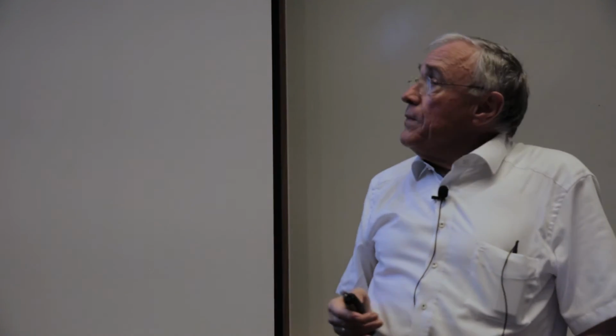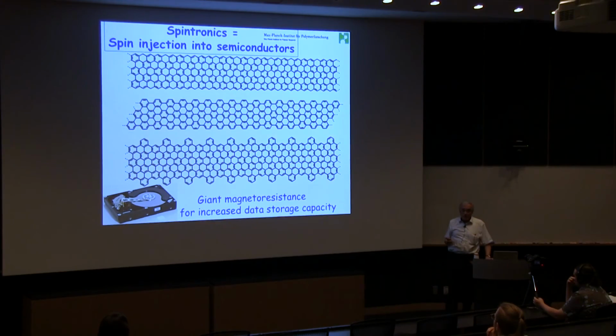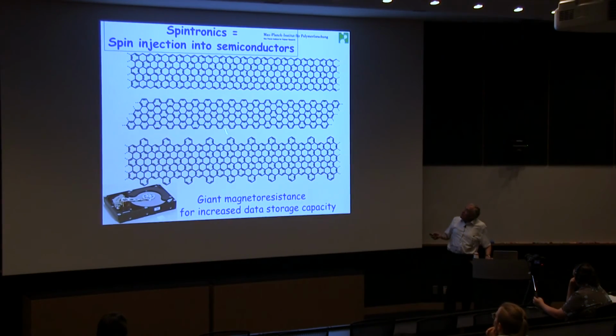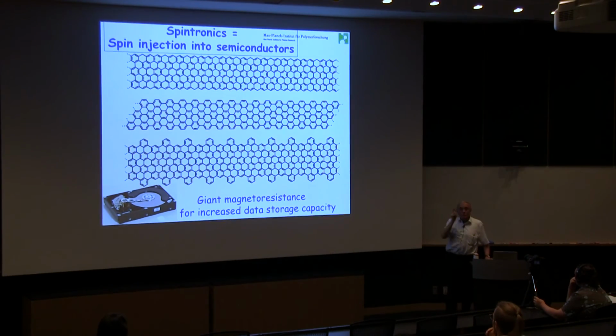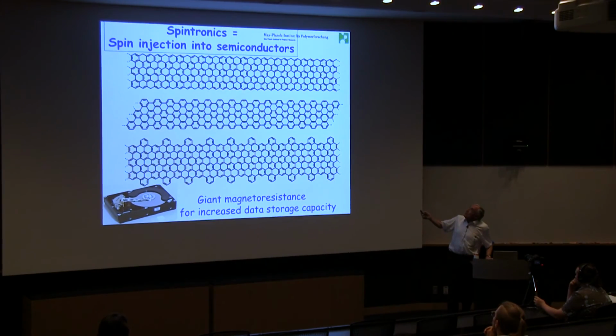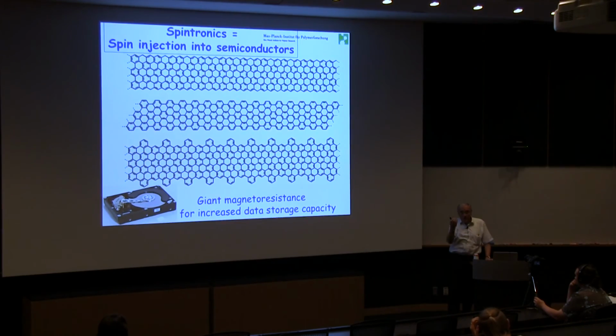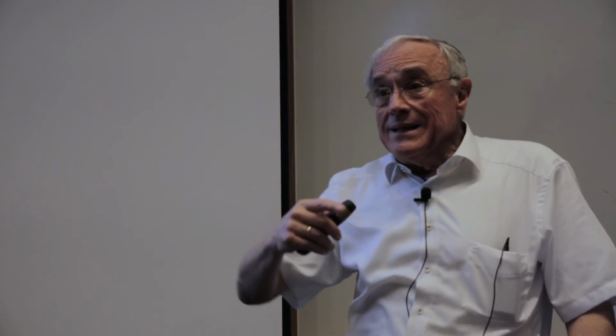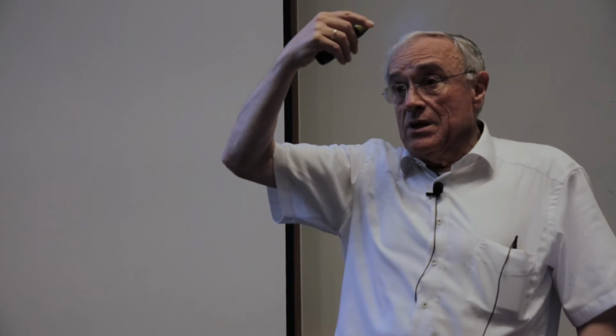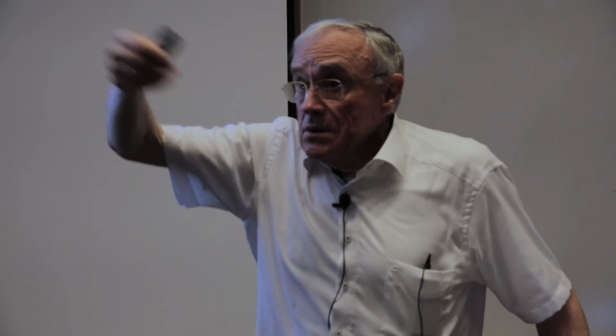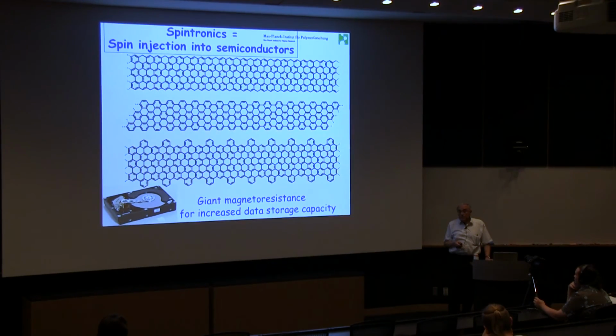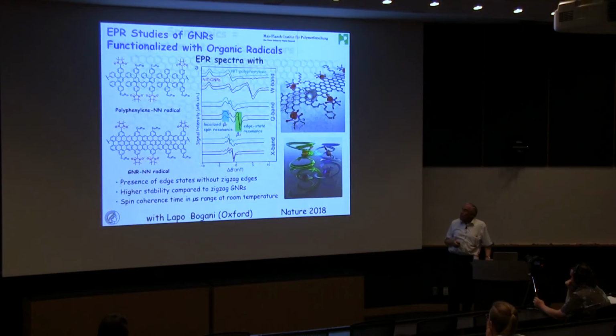The second example, which I unfortunately cannot talk about today, when you look at these ribbons which we make, and we make them perfect, and we make them processable, that you can have them with zigzag states. And at these edges, you have localized electronic states that come with a spin. And that gives you the entry point into no longer injecting electrons into a semiconductor, but also spins. This is also what I would like to mention tomorrow.